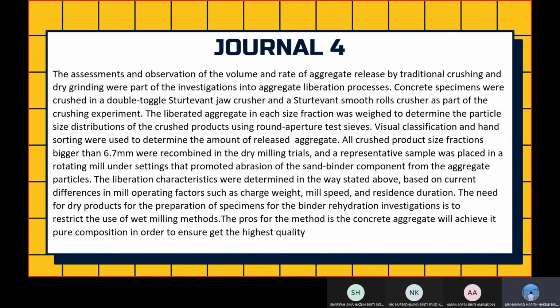So in the fourth journal, the assessment and observation of the volume and rate of aggregate released by traditional crushing and dry grinding were part of the investigation into the aggregate liberation process. Concrete specimens were crushed in a double toggle Sturtevant jaw crusher and a Sturtevant smooth rolls crusher as part of the crushing experiment. The liberated aggregate in each size fraction was weighed to determine the particle size distribution of the crushed product using round-aperture test sieves. Visual classification and hand sorting were used to determine the amount of released aggregate.